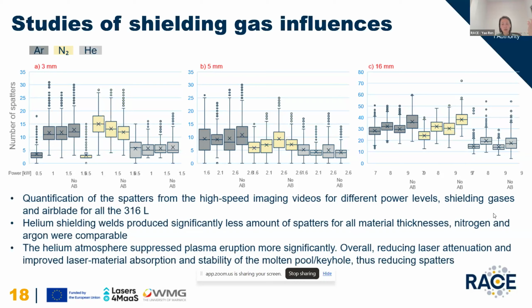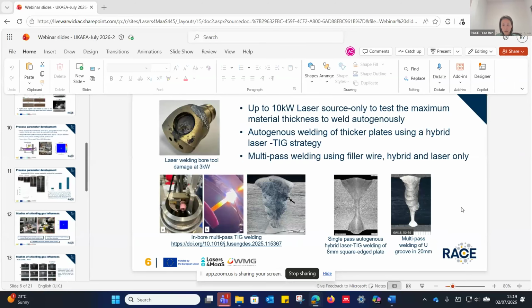Also, as I said before, because of the low attenuation, the penetration is more effective using helium. This is another analysis, not fully completed. We've compared the shielding gas effect on oxidation. Interestingly, at the 5 millimeter fully penetrated weld, nitrogen did give a little higher oxidation, which we don't know the reason for yet. It's being investigated. One hypothesis could be that nitrogen is not fully inert at higher temperature. If it becomes a bit active, probably the performance of the shielding was not as great as suggested.